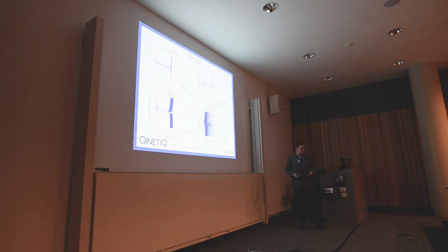So we want to try and understand what is happening at these higher temperatures. So there's going to be some further analysis at these temperatures. We're looking to do some surface analysis, so SEM and TEM, looking at the electrode surfaces for SEI formation and loss in stability of the electrodes. So we're looking for whether the electrodes are still intact or not.